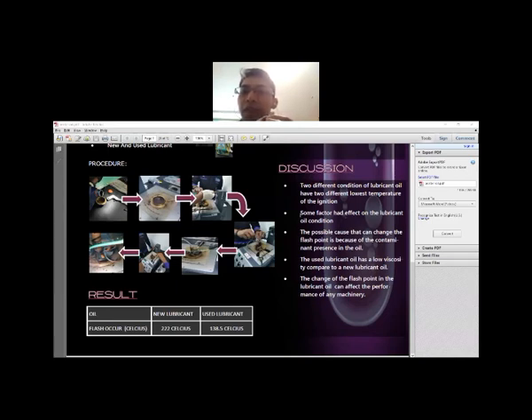This result may be caused by contaminants present in the oil. Also, the used lubricant oil has a lower viscosity compared to the new lubricant oil, which will affect the flash point value. The change of the flash point in the lubricant can affect the performance of any machinery. This means that the used lubricant oil can affect the performance of the gears in any machinery. So that's all, the conclusion.